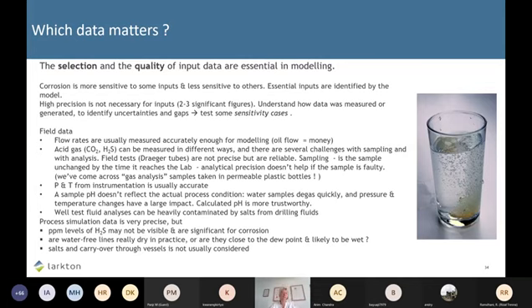Water analysis is another area. We often get pH values given with water analyses. Always just ignore them, because they are taken with, as we show on the right here, the gas depressurizes out of the water, and so the pH values you read are always too high, and if you leave the model to do its calculation of pH, it will calculate the in situ pH, which is a much lower value because it's taking into account those acid gases.